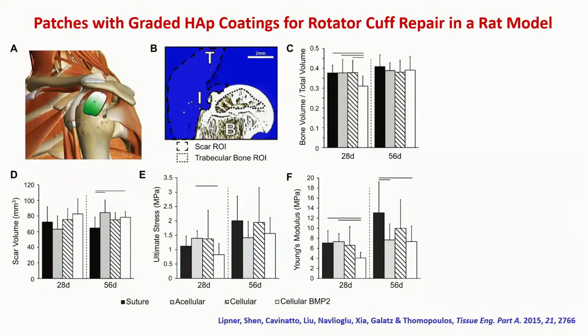And then we applied this to some in vivo studies. We were using a rat model. In that case, you create a defect by detaching the tendon from the bone, and then we suture them together with the scaffold. We call this a patch-based scaffold. We compared 4 different groups. The first group is just a control.